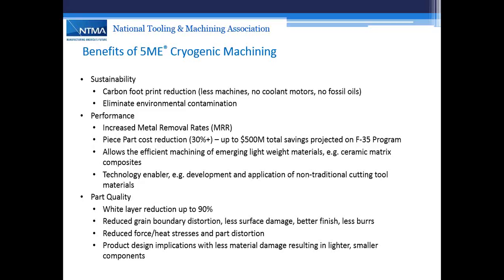Reduced grain boundary distortion, less surface damage, a better surface finish, less burrs. Again, it's the same thing. We're pushing less heat into the base material, therefore less opportunity to smear or drag material. It stays cooler, therefore in a more embrittled state, and therefore can be machined cleanly without a lot of smearing.